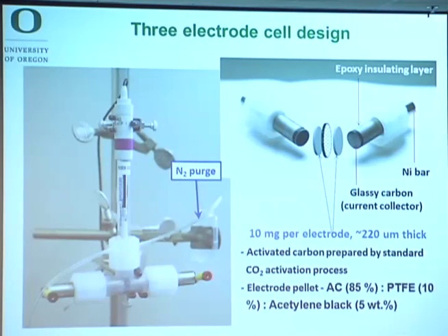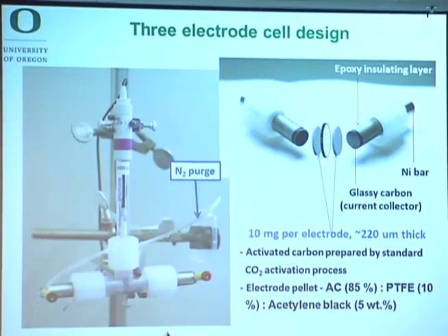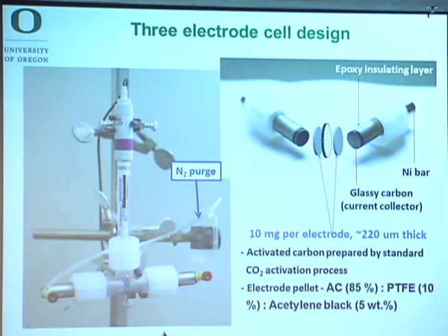Okay, so we designed a special cell to do these measurements, and what's nice about this cell is it's made completely of inert components. This is a glassy carbon current collector with a shroud of plastic. It's contacted to this activated carbon electrode. And here's the separator that separates it from the other activated carbon electrode. And so you can do your normal two-electrode device measurements, while at the same time we've incorporated a third reference electrode so that we can measure what the potentials of each electrode are doing relative to some absolute reference potential. I'll show you data in a second.